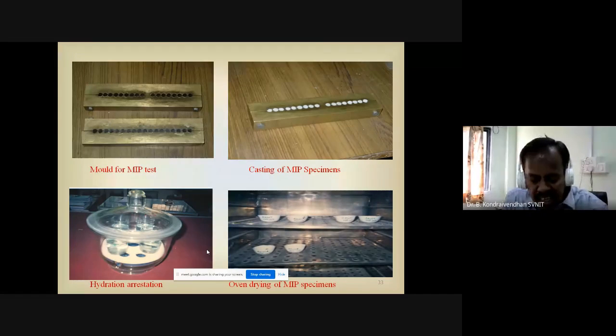After 10 days, you can take the sample out of the isopropyl alcohol and keep it inside the oven at 105 degrees Celsius for 24 hours. Then you take the sample out. Now the pores are empty, there is nothing inside. Now you can store the samples until you do the MIP test.